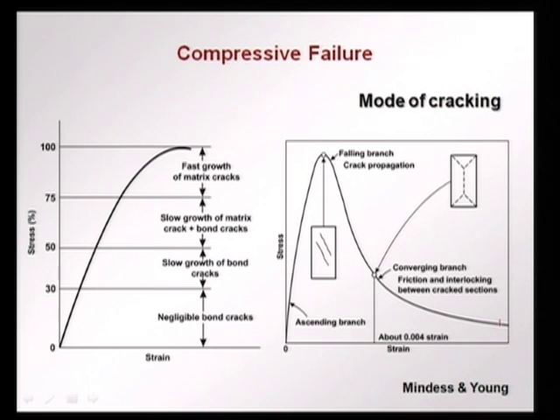So, if we look at how failure occurs under compression, I have discussed this a little bit in the previous slide. Initially there is an elastic response. This is now looking at the axial stress strain diagram. Some bond cracks form in the defects on the aggregate cement paste interface. These cracks start growing, they connect with more bond cracks or cracks start forming in the matrix. There is a faster growth of the matrix cracks, and finally you have the peak load followed by softening.